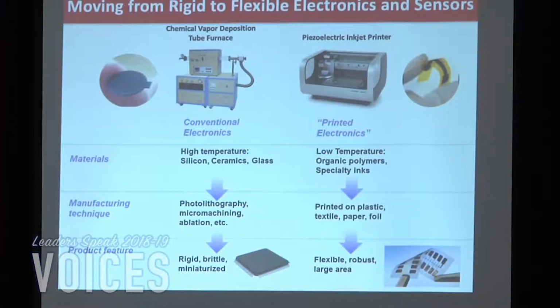So this is a high temperature tube furnace, up to 1,000 degrees Celsius, a vacuum chamber environment. So that can be kind of expensive and costly. And so you need to grow these on materials. Graphene is typically grown on a copper foil, or you have to have some sort of metallic seed catalyst, such as iron, nickel, or cobalt, where the carbon will start to grow from. And those are metals that typically have to be evaporated or deposited on a material such as silicon, ceramics, or glass that can withstand that tube furnace, that high temperature.